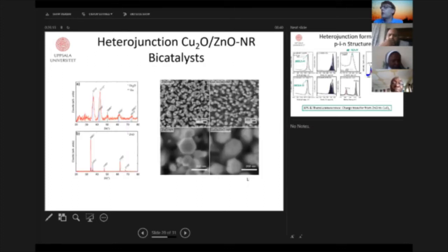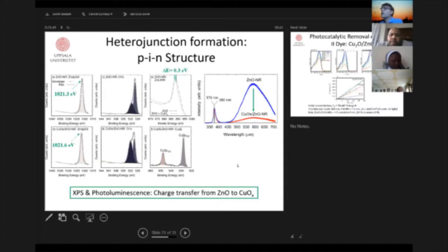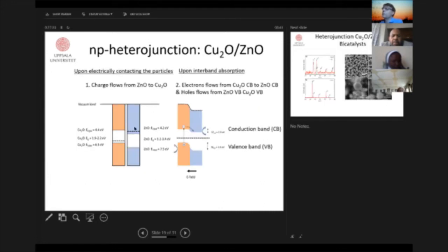In collaboration with Taltech in Estonia, we deposited copper oxide on zinc oxide nanorods. This is a bare zinc oxide nanorod, and here they're covered using a technique where we land small clusters of copper particles and oxidize them on the surface of the zinc oxide. This is an electron microscope image, so you get a picture of what we are doing. We formed this PN structure, this junction, shown by both photoelectron spectroscopy and photoluminescence. We have a shift in the zinc states and also in the Auger transition of 0.3 electron volt, pointing to a charge transfer from zinc oxide to copper oxide, as I indicated here. This is what we expect to occur.